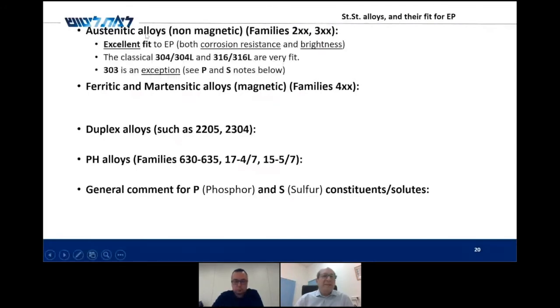For austenitic, they are an excellent fit to electro-polish, both in terms of corrosion resistance and in brightness. The classical 304 or 304 low carbon, 316 and 316 low carbon are very fit to electro-polish.